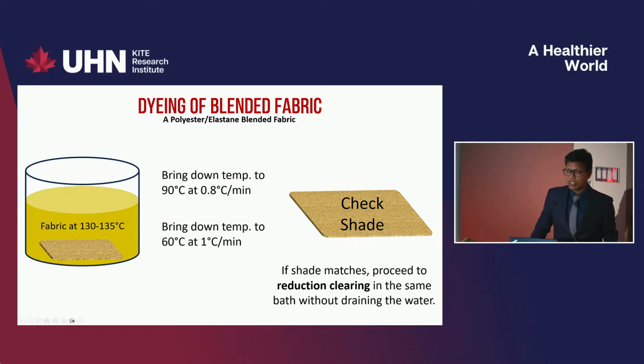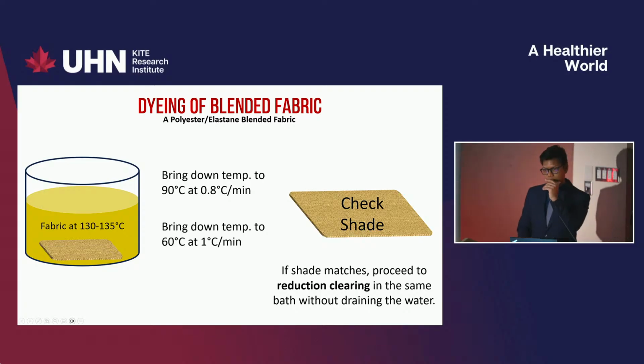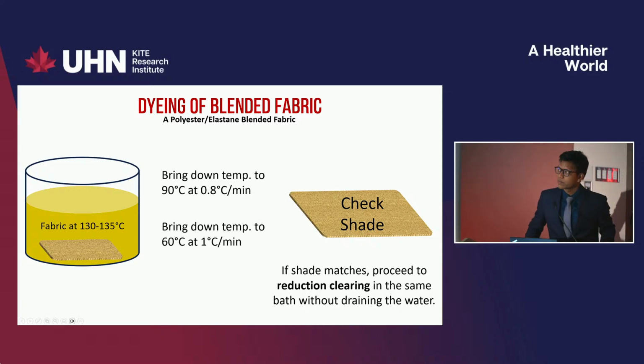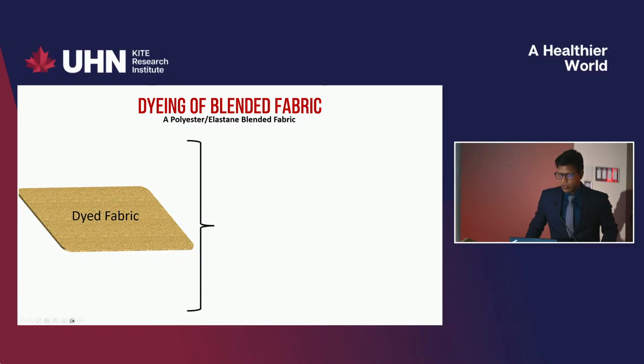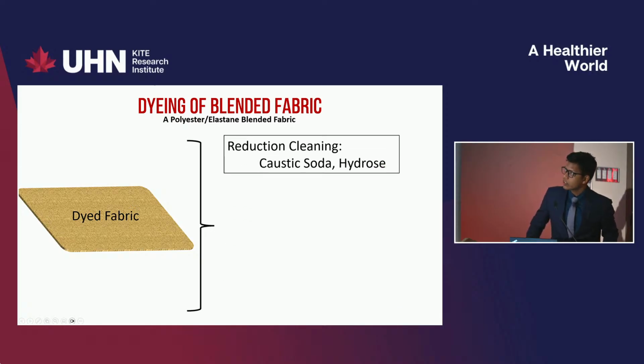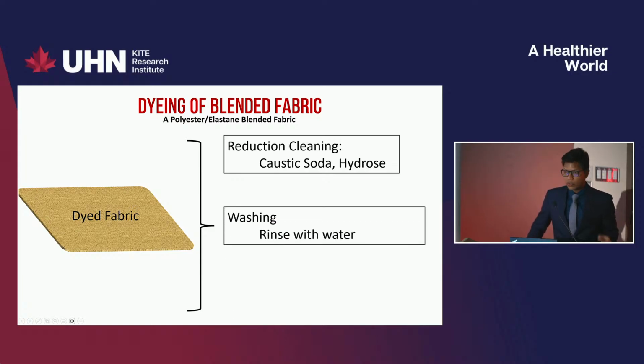If we are satisfied with the shade we want, then we go for the reduction cleaning. The reduction cleaning process is very important when you are talking about polyester fabric dyeing, because as I said, the dyes we use for the polyester and elastane is dispersed dye. It's not chemically bonded. We physically insert the dye inside the polyester fiber. So there are some dyes which still remain on the surface of the fiber. So we want to get rid of this remaining residual dyes so that there is no question after we sell the product to the consumer. So for the reduction cleaning, we do 3 different steps. First, we use caustic soda and hydros to get rid of the surface dyeing.